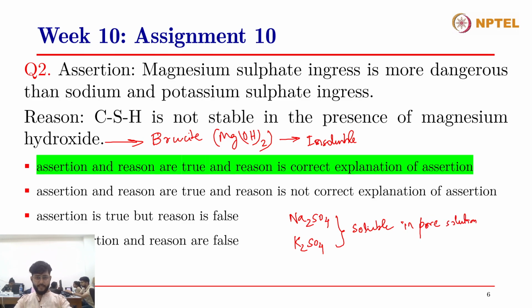Now, when an alkali sulfate is soluble in the pore solution, it maintains the pH at a higher level. In order that the cement hydration reactions progress in a certain manner, the pH of the pore solution has to be maintained at a high level, of the order of 12 to 13, right? When the alkaline earth sulfates are present inside the pore solution and react with the hydroxyl ions, as in the case of magnesium sulfate, it produces magnesium hydroxide that is insoluble in the pore solution. Brucite is precipitated inside the cementitious matrix, and the pH decreases. So, due to its insolubility, the pH decreases.